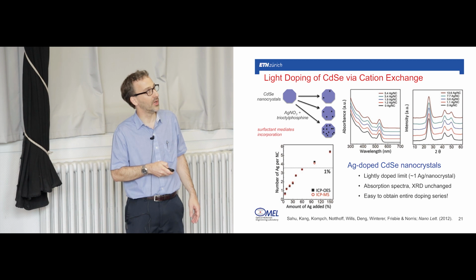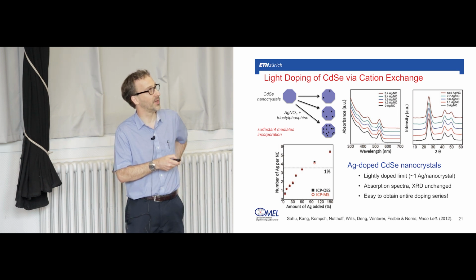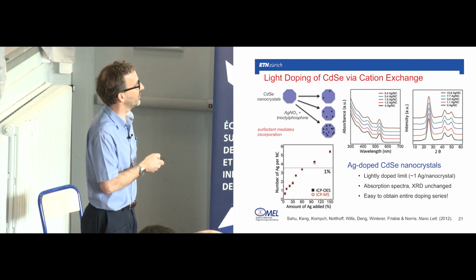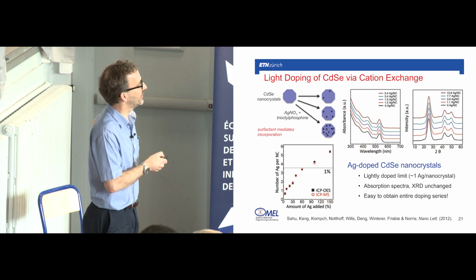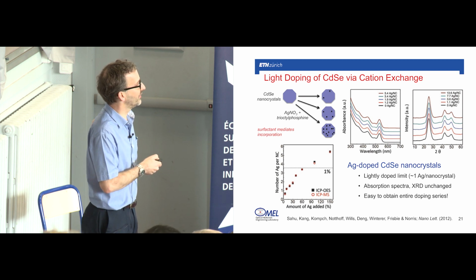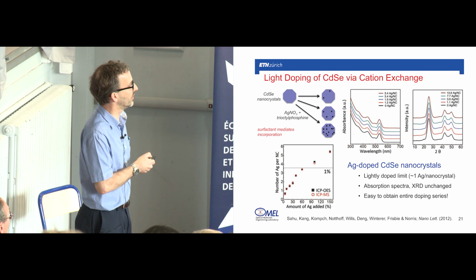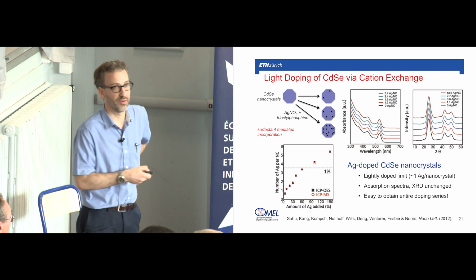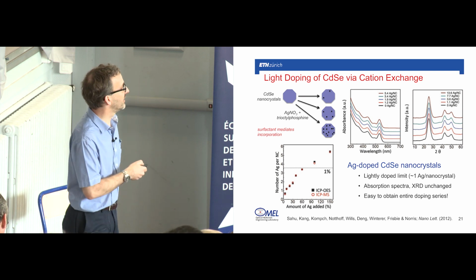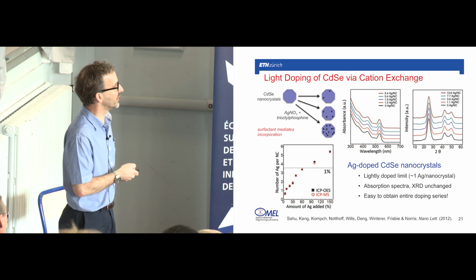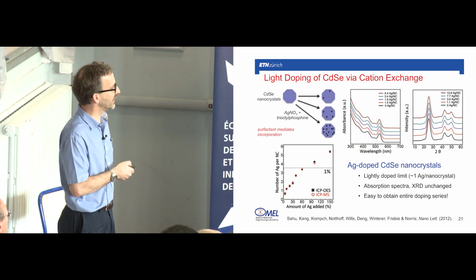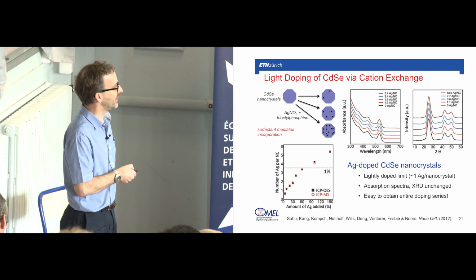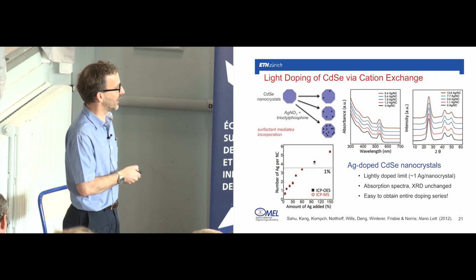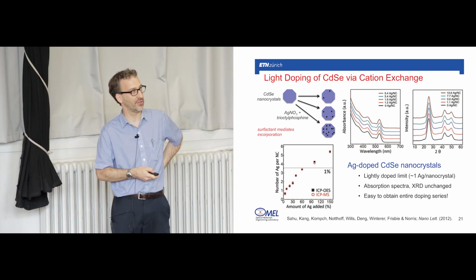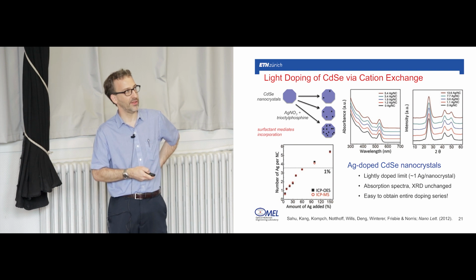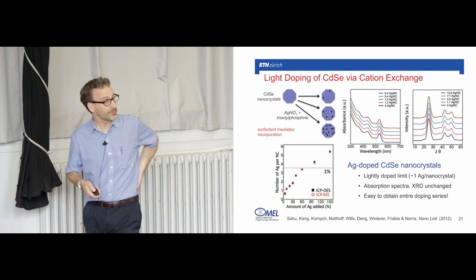So Ayash Sahu, a PhD student of mine that just graduated about a year ago, found that it was fairly straightforward to basically dial in the number of silver impurities that you want per particle by adding some trioctylphosphine. So this surfactant presumably mediates the incorporation. And by doing elemental analysis, he could measure the number of silver per nanocrystal on average as a function of the amount of silver, and you could just dial in the number that you wanted.